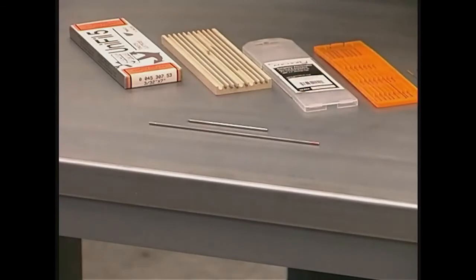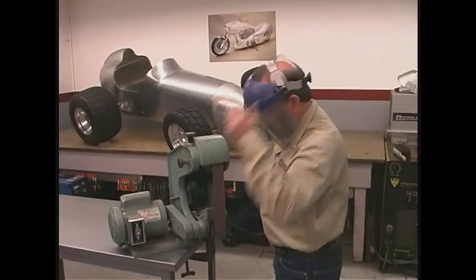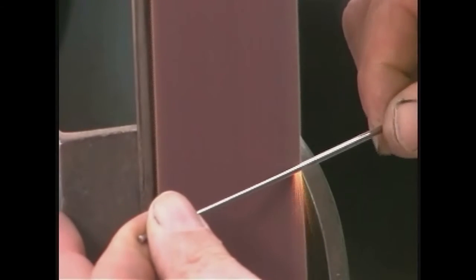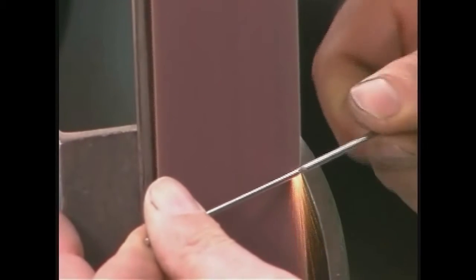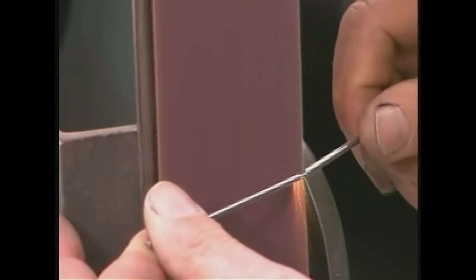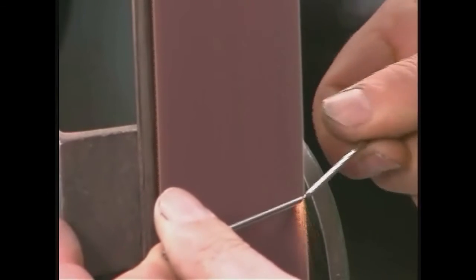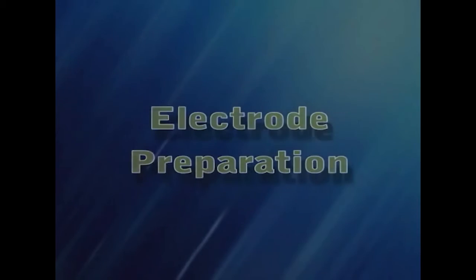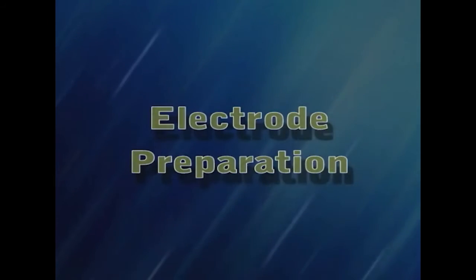And you'll have to cut the tungsten a little bit shorter to use the smallest end cap. It's best to sand or grind through the tungsten to shorten it. They can shatter if you try and break them. Or even if they don't shatter, it can split the grain of the material, which causes problems with the arc later on. Remember, they're only color-coded on one end, so if you cut them in half, one part will be unmarked. Now let's talk about proper electrode preparation.